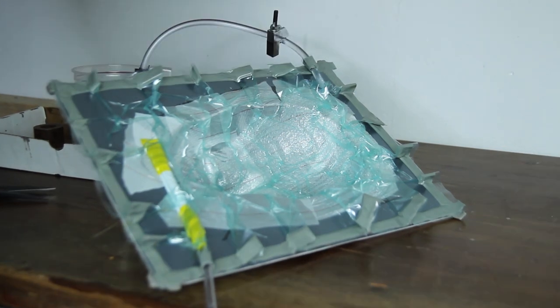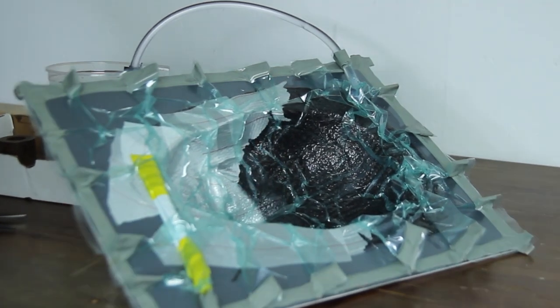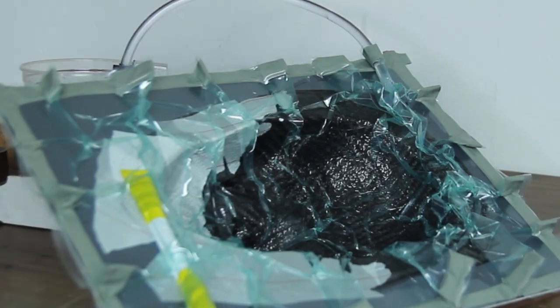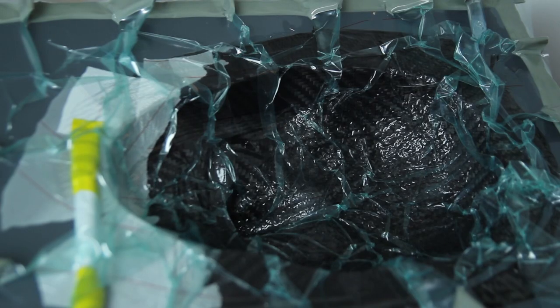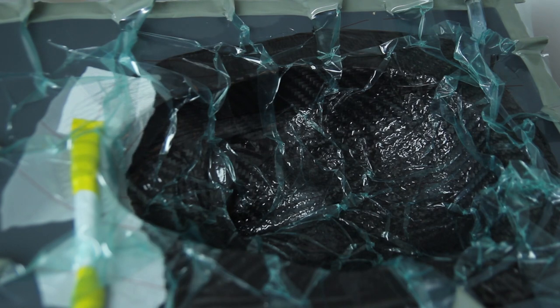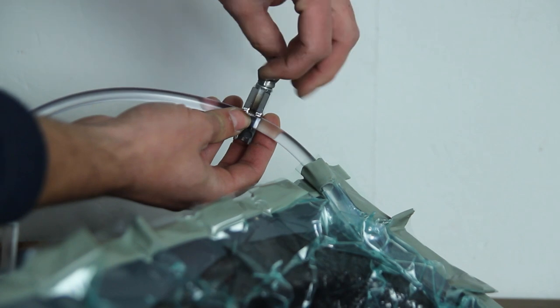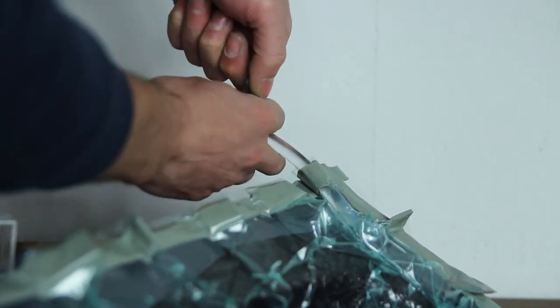So I'm just opening the line right here, and then you'll see the resin going all the way through. So this is helped by vacuum and it's being sucked all the way through the part. So once you're reaching the other side, so once the resin has went all the way to the resin out, so the vacuum side, you can close the clamps and just leave it to cure.